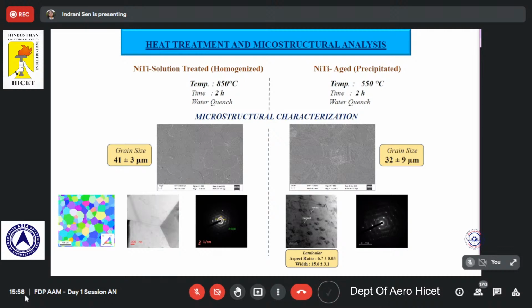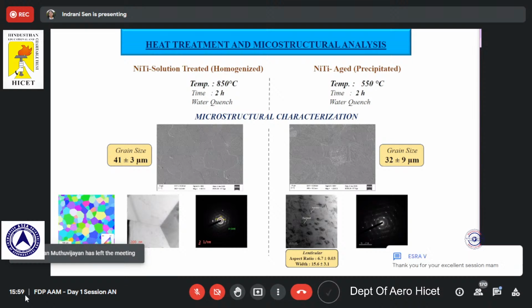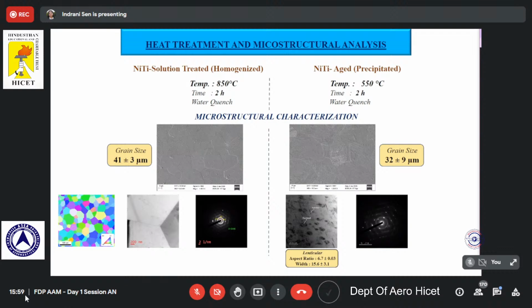The combination of twinning and martensite is a known concept; what about the precipitate and martensite combination? I'm not getting your question, Mr. Natraj. Both are there, as you have shown in the slides, ma'am. Yeah, so both are different phases. Twinning and martensite are not two different phases. Martensite is in a twinned condition; both the twins are martensite only. That is a single martensite phase, but precipitate is a separate phase. Phase is when it has a different crystal structure or different compound altogether, right? So the precipitate here is nickel Ni4Ti3. That's a separate compound with a completely different crystal structure than the martensite.